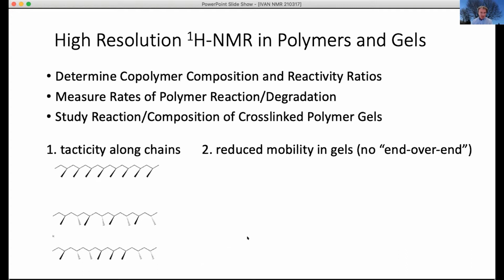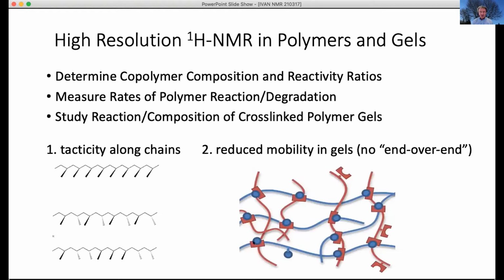In addition, when you cross-link these polymers, even though you have linear segments that may be swollen and quite mobile, think of people skipping rope, what you cannot have is end-over-end reorientation on the NMR timescale. So there is residual anisotropy, usually due to dipolar coupling, that we have to deal with. You'll see that we use magic angle spinning to eliminate that.